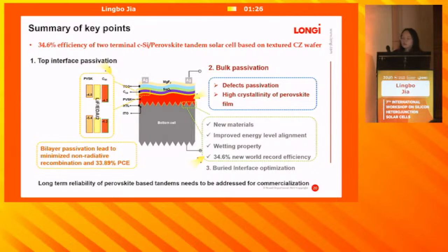And finally, we focused on the buried interface optimization. We introduced new materials we designed, and these materials can improve the energy level alignment, and also they have good wetting properties. So finally, by using these materials, we achieved a 34.6% new world record efficiency. And although the efficiency of silicon solar cells is high, the long-term reliability of perovskite-based tandem solar cells also needs to be addressed for commercialization.